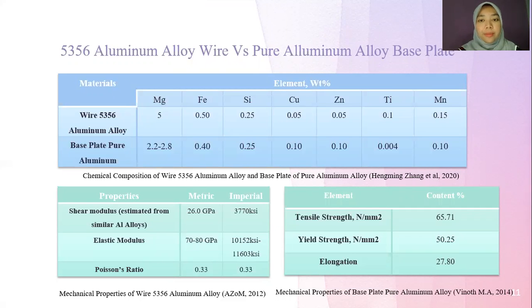The dimension of the base plate that will be used is 100 mm length, 25 mm width, and 10 mm thickness. Before the deposition, the base plates were washed in alkaline water and dried in air, followed by mechanical cleaning and degreasing with acetone immediately before usage.